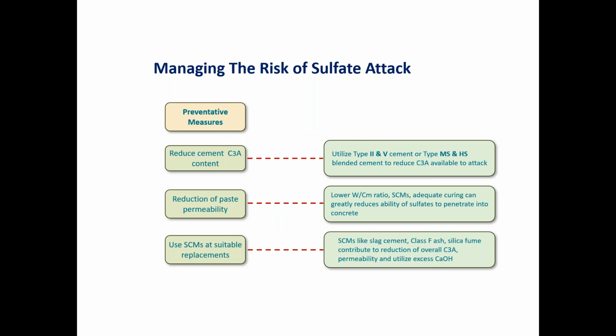Okay, so managing the risk of sulfate attack. Here are a few common themes of things that are approached when it comes to managing sulfate attack. This is obviously on the premise that you have some sort of sulfate exposure level that's greater than 0. Here are some of the things that are done. Reducing the cement C3A content. We said that's a foundational part of sulfate attack. You reduce the C3A, you reduce the amount of hydration product that is highly vulnerable to attack by sulfate. This is accomplished through things like type 2 cement, type 5 cement use, or moderate sulfate and high sulfate resistant cements, which are blended cements that meet a performance spec.